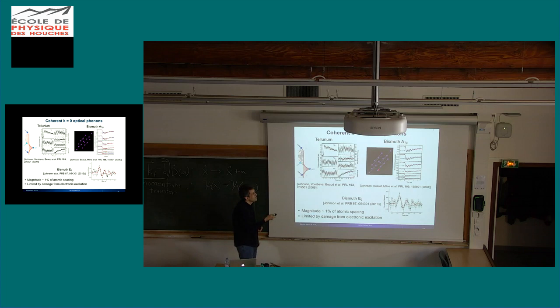I should point out that these are all examples of indirect excitation, where you're driving the phonon dynamics by exciting electronic states, and then these electronic states couple to a displacement of the potential energy, which is why you see this. They're long-lived excitations, which makes it mathematically displacive, and so that's why it shows up as a displacement and an oscillation around a new minimum.